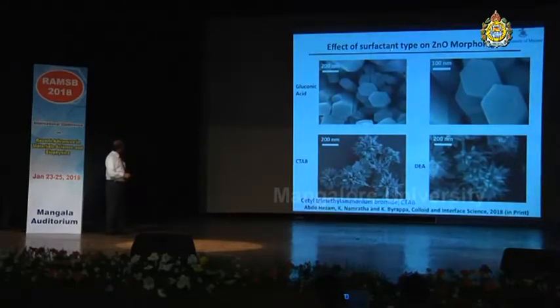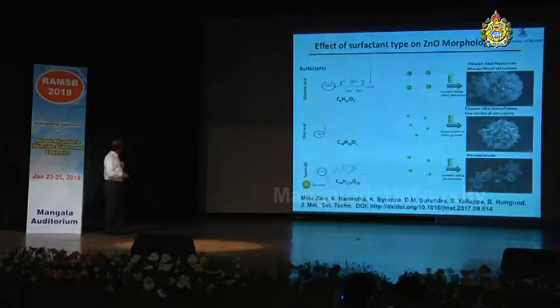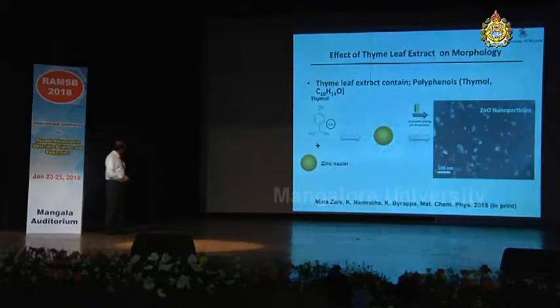The effect of surfactant on the zinc oxide morphology is shown here in this wave block with different surfactants like gluconic acid, CTAB and DEA, and this is CTAB and diethanolamine, and they show different morphologies depending upon the concentration and the type of surfactant. And here you can see the gluconic acid giving these flower-like nanorods and some hierarchical structures, and oleic acid giving this suppression of 001 growth, and Tween 80 giving this typical morphology for zinc oxide.